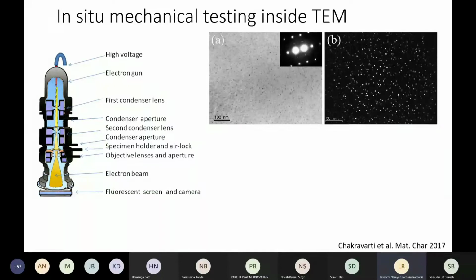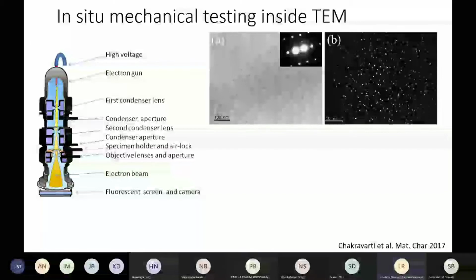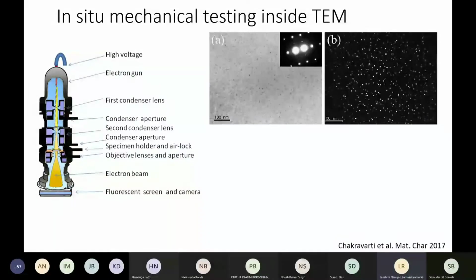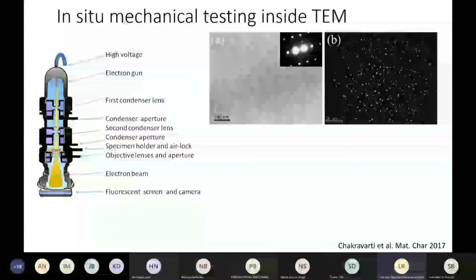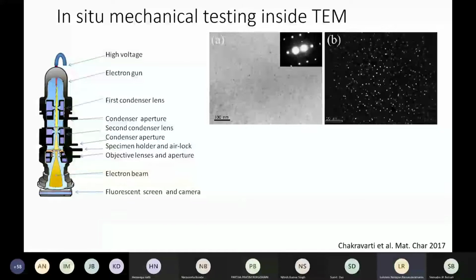TEM has another mode where you can get diffraction information. What really happens is William Bragg came up with a concept that materials at the crystallographic level can also diffract light or radiation or electron beams. And this diffraction will give us a lot of information. What information does it give? It gives us crystallographic information. In crystals, when they have regular planes, these planes act as diffraction slits or diffraction gratings, which can cause interference in the electromagnetic radiation, which is your electron beam. And these interference patterns essentially are captured at the fluorescent screen, and these appear as a spotted pattern. Because your electron beam is also a spot, these spots are diffracted spots.